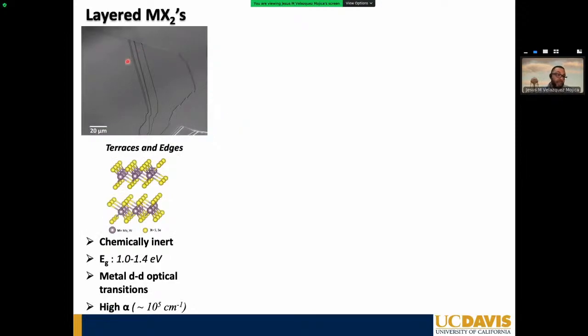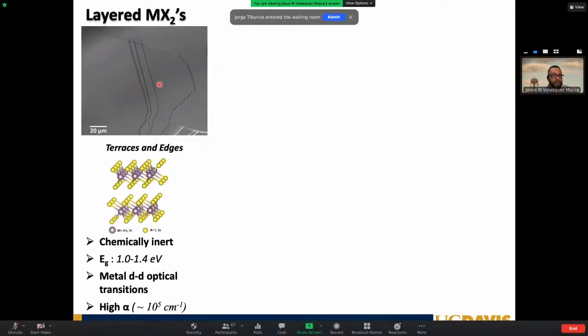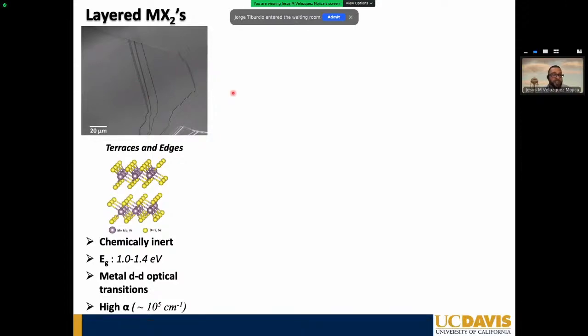As you can see here from the SEM, you're seeing these flat areas and literally these steps that I'm showing you here with the laser pointer. This is what we call in the community etch sites. And etch sites are nothing more than just dangling bonds, so under-coordinated sites. So if we're talking about molybdenum disulfide, you are going to basically find that the termination of that step edge is going to be a metallic molybdenum. And they've been highly studied, and it's just an explosion of interest for the past couple of decades, but specifically thanks to some of the ideas that we've gotten with being able to synthesize graphene.